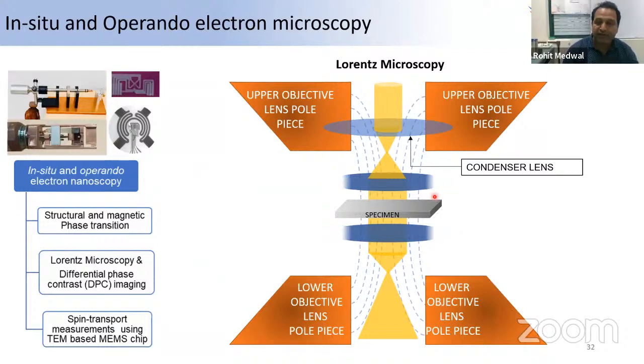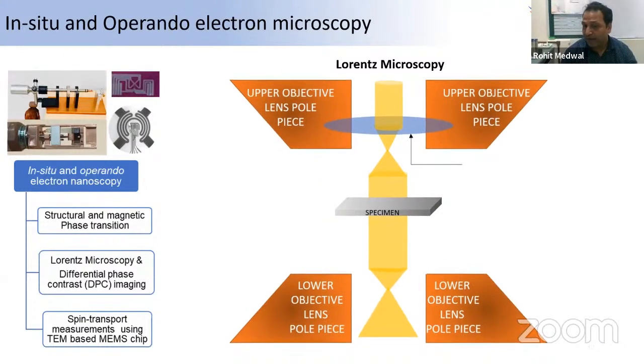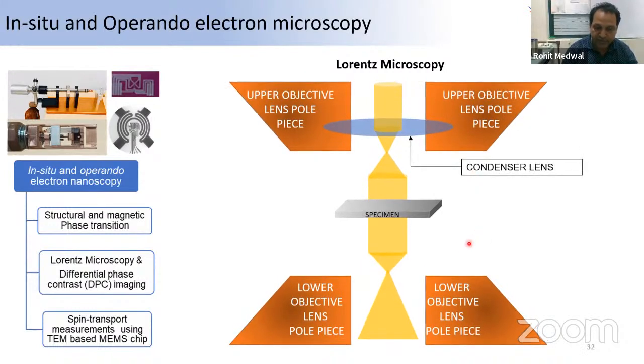So we have a special TEM, which we call the Lorentz TEM. We turn off this objective lens. We have another objective lens, the lower one, which we call the Lorentz lens. So the specimen is under field-free conditions. There is no external magnetic field on the sample. And the beam passes through the sample and carries the magnetic information, and we focus this beam and then do the imaging.